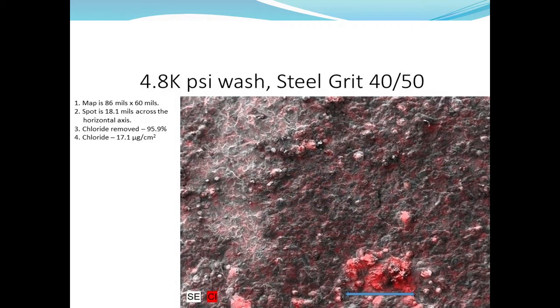Here is another clumping. So what we're saying here is that as long as you can measure chlorides even down to 5 micrograms per square centimeter, which most people would tell you is plenty sufficient to put coatings over, we've seen in the lab that even at low levels you can get early coatings failure, and it's because your chlorides are concentrated. It's like if you had a 15-inch pizza and a single grain of salt in the middle of it, but it's salty enough to salt the whole thing. But it's all focused in that one spot. You'll get a corrosion cell there, and then it'll grow.